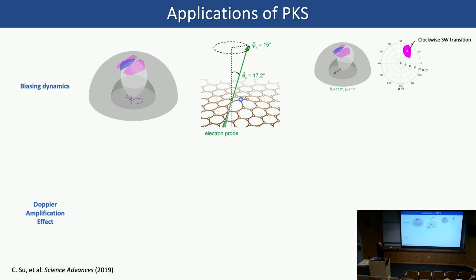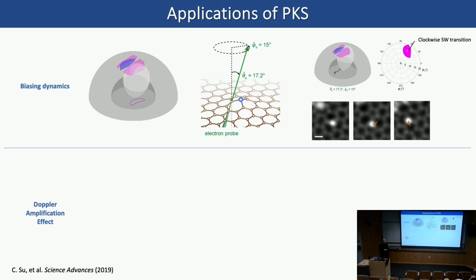dynamic outcome into one certain type of atom dynamics instead of having all the other atom dynamics happening all the time. So we did an experiment. We put the electron probe, tilted a little bit in this way, and according to PKS, it only intersects with the clockwise Stone-Wales transition. And this is what we see actually in the experiment. We see that it only has this Stone-Wales transition that happens once you place the electron beam in that way, without having the direct exchange or other kinds of, or even a counterclockwise Stone-Wales transition. So this is a proof of concept, how you could use PKS in a simple way to visualize the outcome.